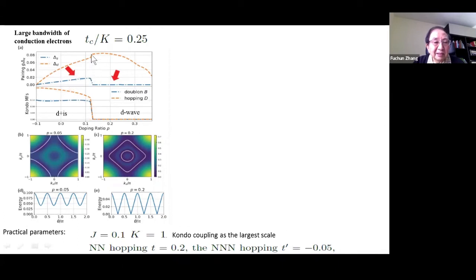So actually you can see two regimes. In the lower doping regime, I have both components of D and S, okay. The lowest energy state is given by D plus iS, because that makes the gap larger, okay, to gain more energy. However, as you increase doping, at about 0.15, okay, the S wave pairing disappears, and the D wave pairing is enhanced like this, okay. So that means in this regime I have D plus iS, and in this regime I have only D wave part. Okay. In the calculation, we make a simple assumption that we fix the number of conducting electrons, like 5%. Okay, so we do not change.